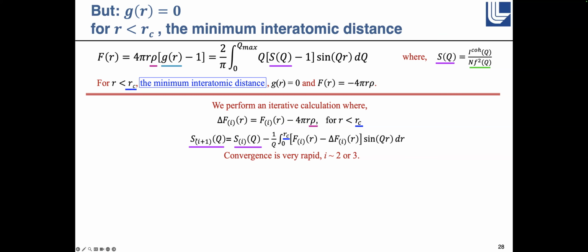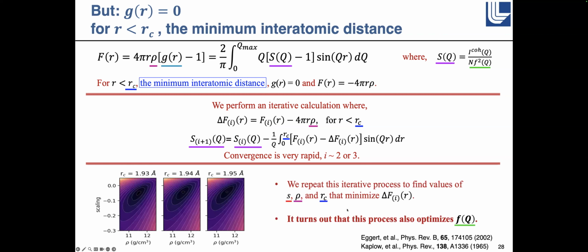So then we take this new structure factor, we Fourier transform it to get the new f of R, and we repeat this. And the convergence is very rapid, 2 or 3 iterations, and I'll have an example of that in a slide. And then we repeat that with different values of S, rho, and the critical distance, and we try to minimize this delta f of R. And so basically, we're trying to get G of R to have a radius where it goes to 0. And it turns out that when you do this, you also optimize the atomic form factor. And so I did this in 2002 following a paper that was written in 1965.